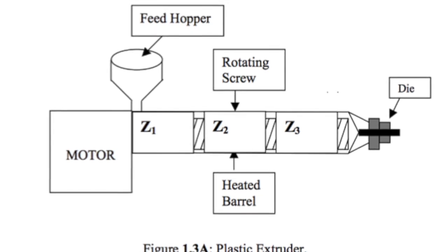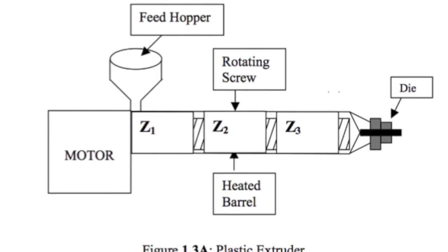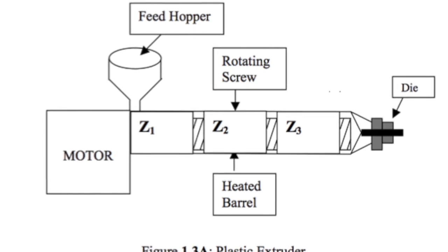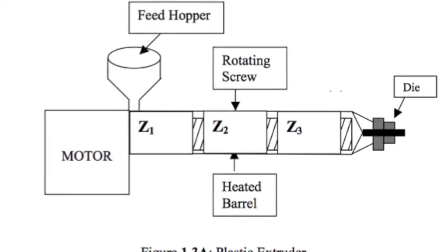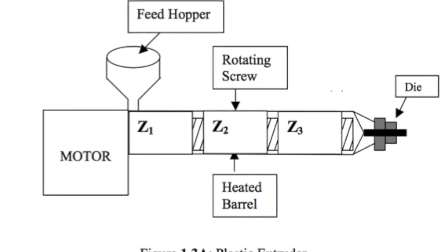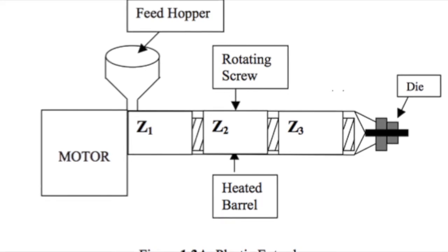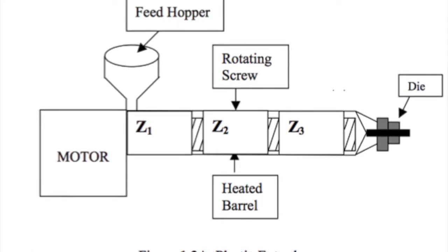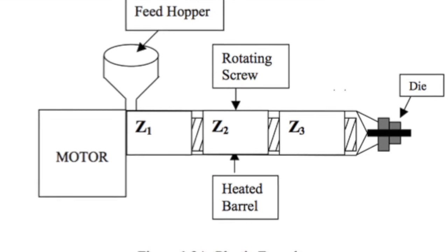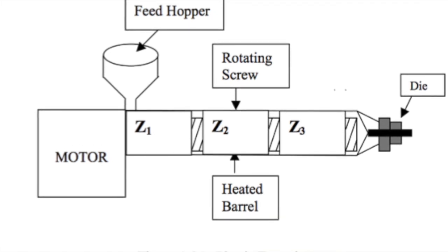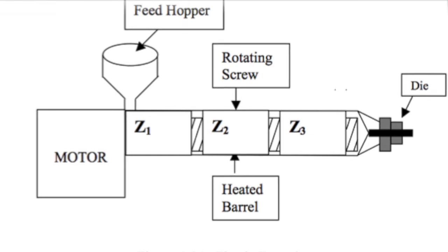The extruder contains 3 sections. The first section is maintained at a relatively low temperature. The second section is where the melting occurs and pressure is built up. Finally, the extruder outlet is the metering section. At the end of the barrel, the melted plastic leaves the extruder through a die which has been designed to give the desired shape to the stream of the melted plastic. The polymer viscosity is dependent on both temperature and flow rate.